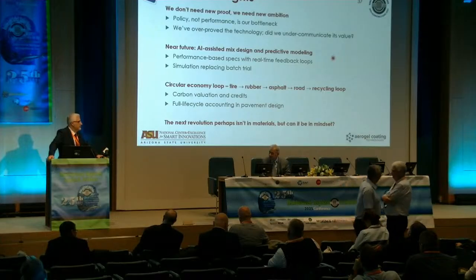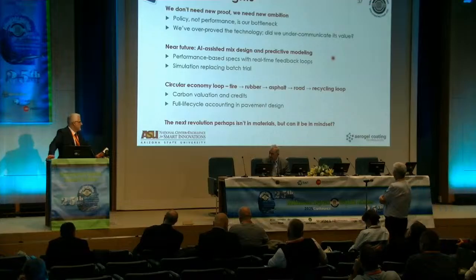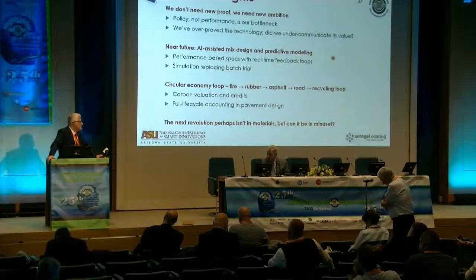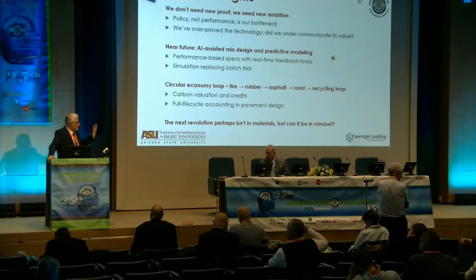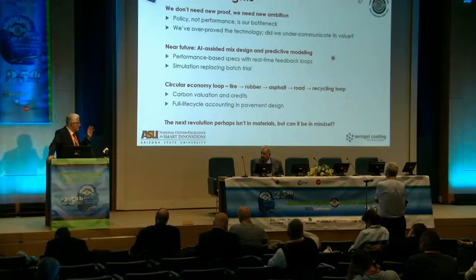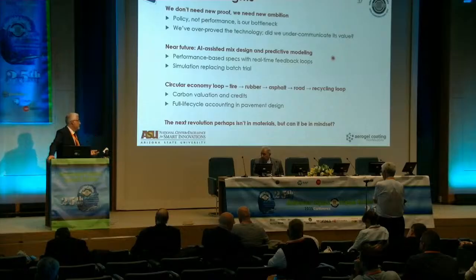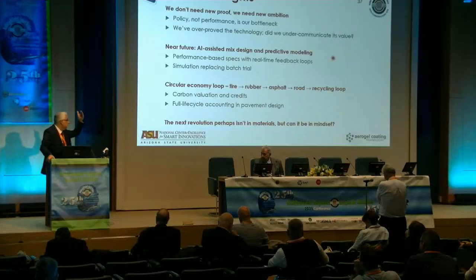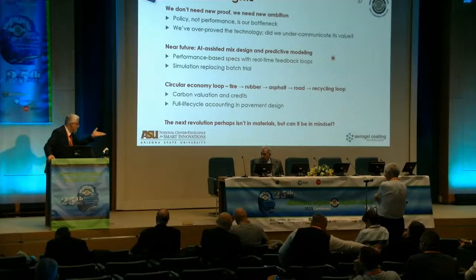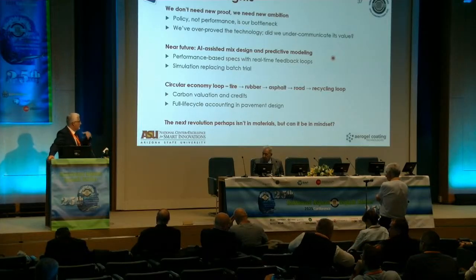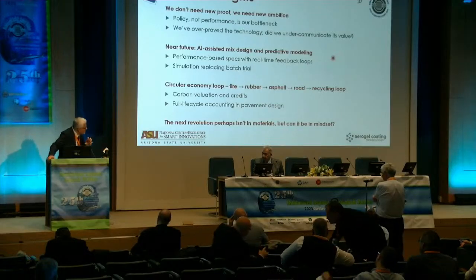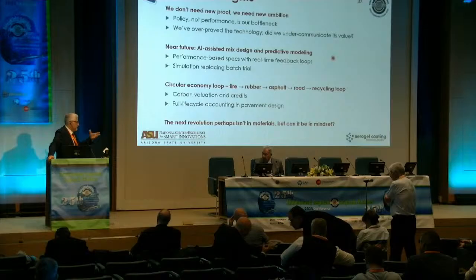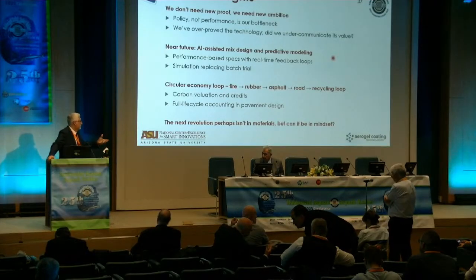The temperature might stay at a certain value depending on thick versus thin designs, and we have different scenarios for how to do things. But I'll give you an example: the concrete with the porous asphalt on top. What we have found is that the average temperature of the concrete stays higher than typical without the cover, but the temperature differential from top to bottom is reduced, and that's what we are after. How to reduce the temperature changes in the layer in order to minimize the thermal stress you just talked about. So absolutely, it's a thermal fatigue stress, but we shield it from that, and the way to do this is by designing a certain amount of particles in there to achieve that.